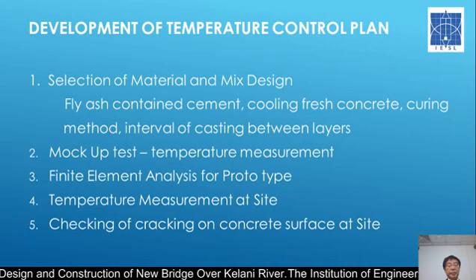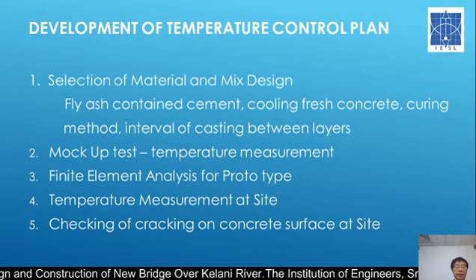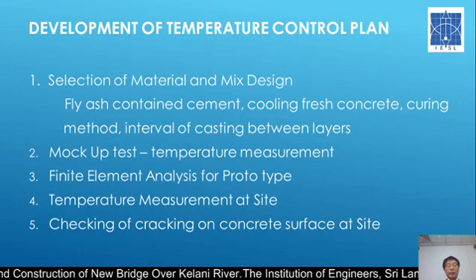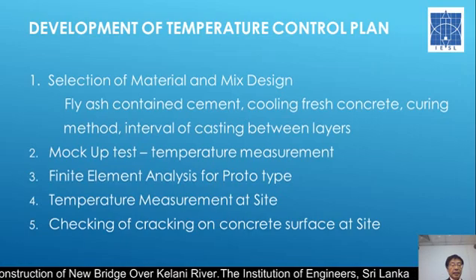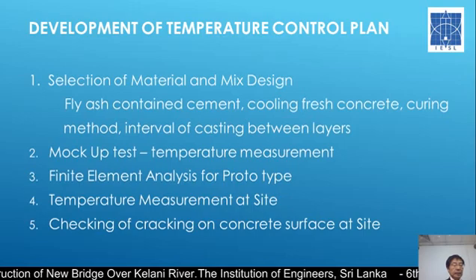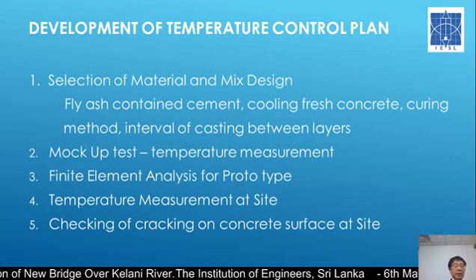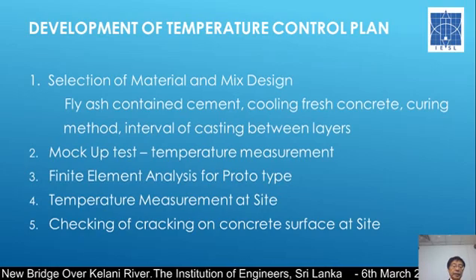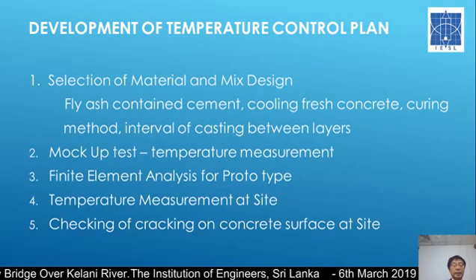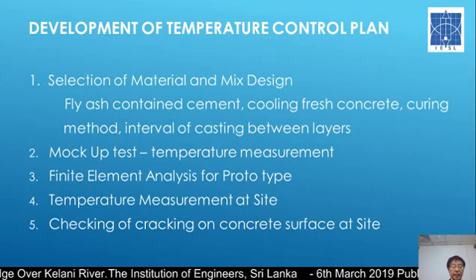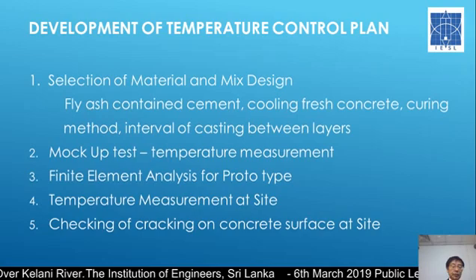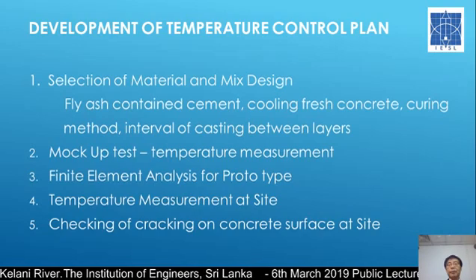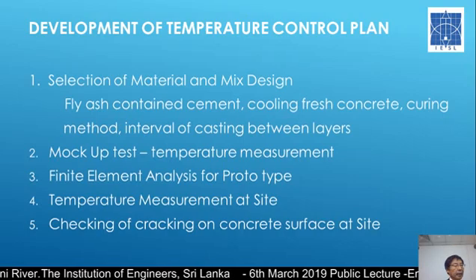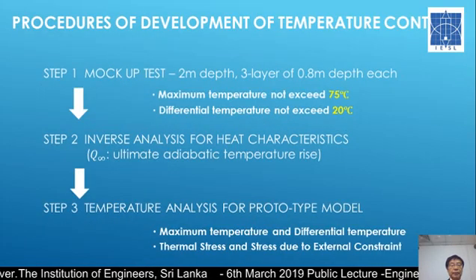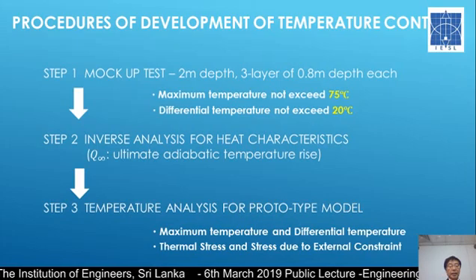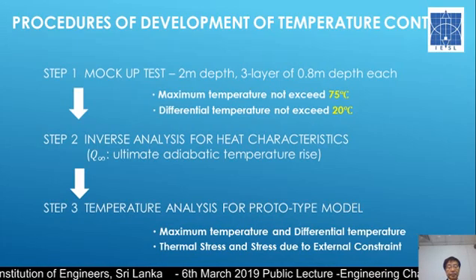So after selection of the material and mix design, the mock-up test is to be done, and the temperature measurement for the mock-up specimen is to be done. Thirdly, with that result, the finite element heat analysis is done for the actual structure. With that, the concrete is cast for the pile cap, and the temperature measurement was done at the site. And finally, after the casting, as I mentioned, the concrete surface should be checked for any harmful cracking, especially thermal cracking due to the temperature difference. So mock-up test, analysis, temperature measurement, all these are done.